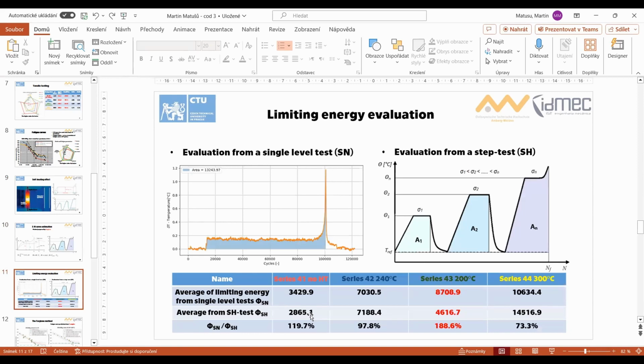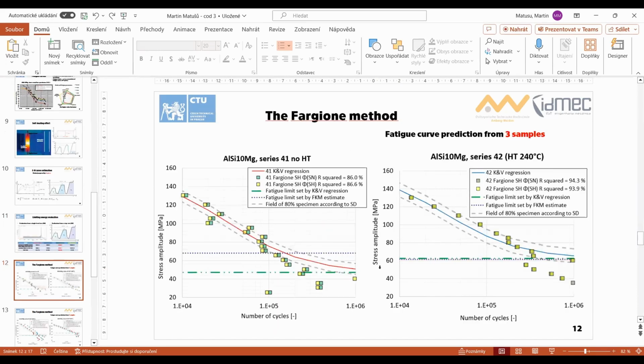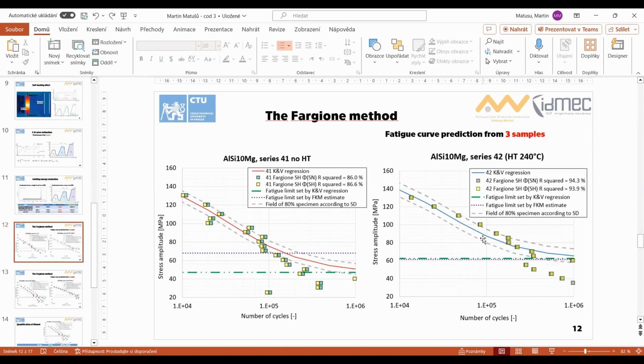So we were trying to look at this. We put the average value of the limiting energy from the single level test, from the normal test, on the left side, as you can see, and as the summation from the self-heating test. And we come up to results that are quite interesting, because if you take the limiting energy for the 41st, 42nd, and 44th series, the differences in the estimations are not that big. But for the 43rd series, there is a huge deviation, which we were not able to find out why. But here is the estimation, as you can see here.